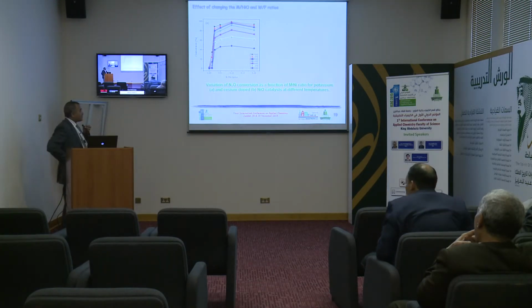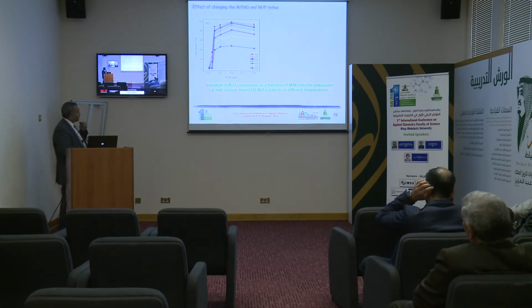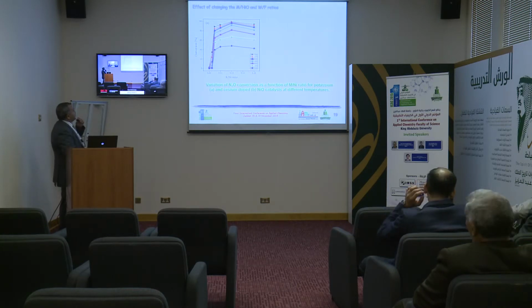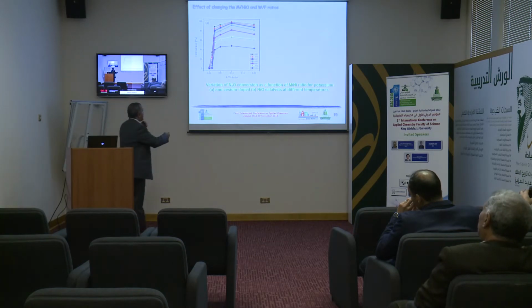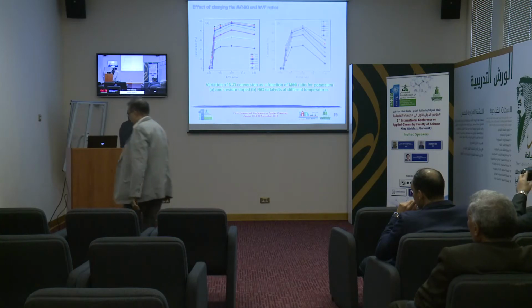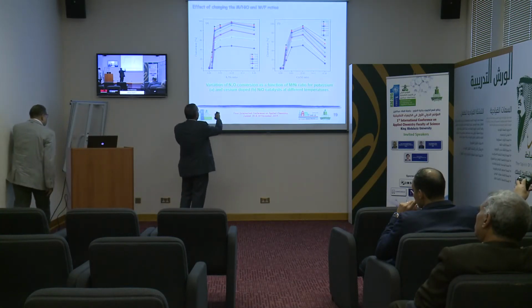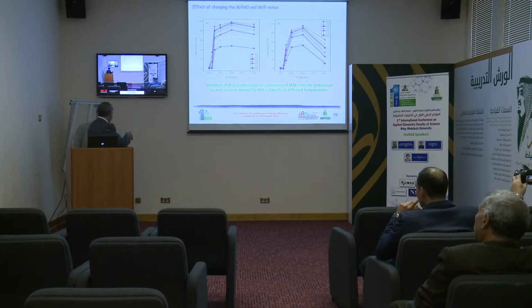Pointer? Yeah, okay. So we went now to study the second part of this presentation, which is the effect of changing the metal to nickel oxide ratio for the two most active catalysts, which are potassium and cesium. We checked the effect of changing the dopant concentration. We can observe here that the higher activity was obtained for the catalyst that contains a potassium or cesium to nickel ratio of 0.1.